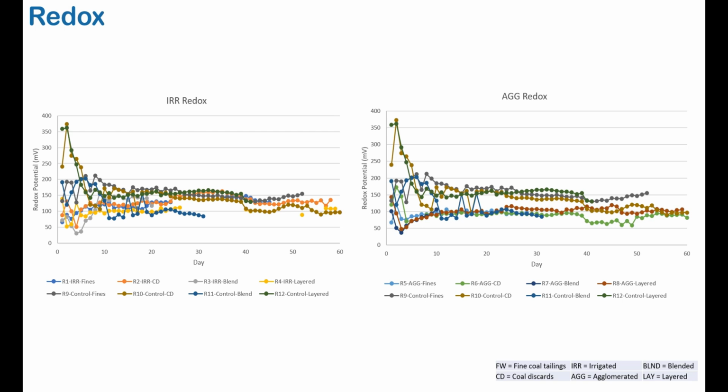Although no studies have investigated the redox conductivity of MICP reactions, it can be assumed that the calcite-forming reactions occur within the 100 and 150 millivolt band. The exact redox couple that causes this phenomenon is unknown, and studies are being conducted by us to elucidate the relationship between redox conductivity and calcite generation. Taken together, it can be said that MICP occurs in these mine waste bioreactors at pH values between 8 and 9 and redox conductivity values between 100 and 150 millivolts.